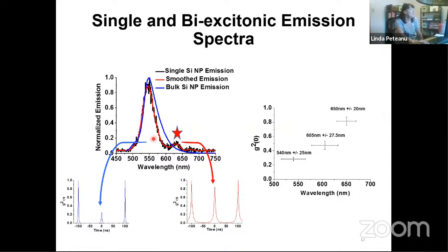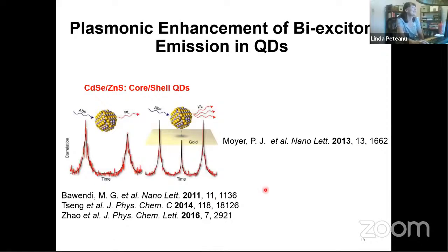If you do photon statistics in solution of the type I just talked about, and you wavelength select, say I'm only going to look at the emission from this state, I get a pretty high contrast, with relatively few counts at t = 0, or high contrast anti-bunching. If I focus only on this region with a filter, I get almost equal intensities between these bands, showing a low degree of anti-bunching, a high degree of biexcitonic character. If I plot it as a function of wavelength, I can see that the biexcitonic character increases to the red, as I would expect for something derived from the silicon core. Just say, 2 minutes rather, sorry,